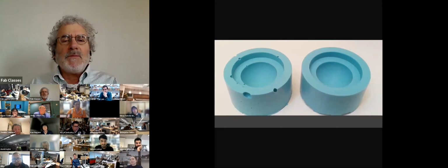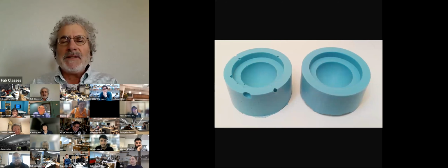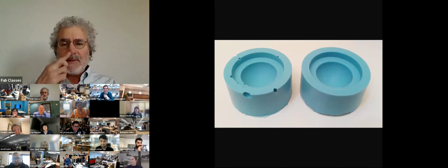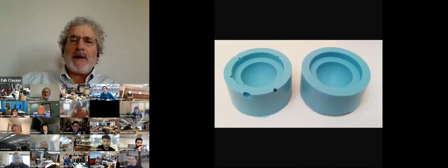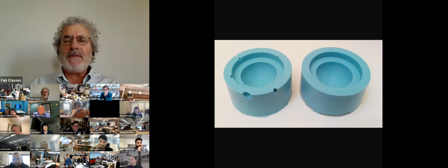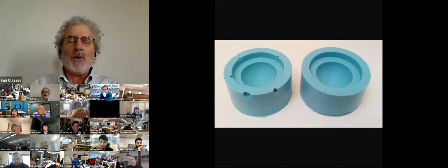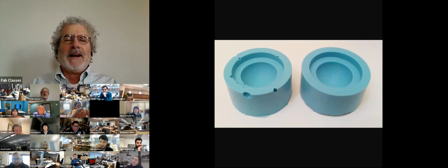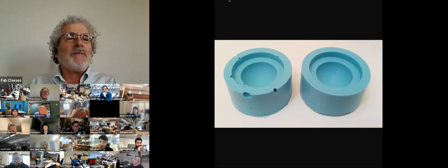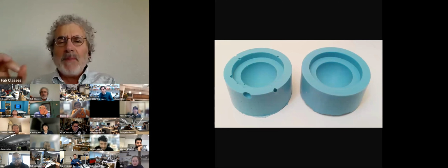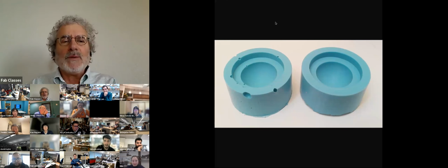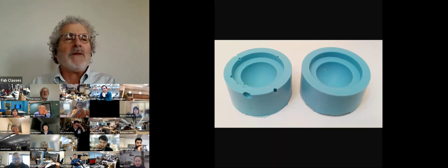So one of the main challenges this week is bubbles. If you mix it by scooping, you drive in air. If you dump it in the mold, you drive in air. And so there are many different ways you drive in bubbles that then get trapped in the mold. If you do everything right this week, you have a beautiful, smooth, featureless mold.